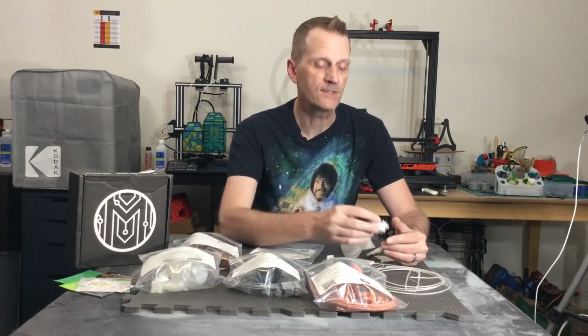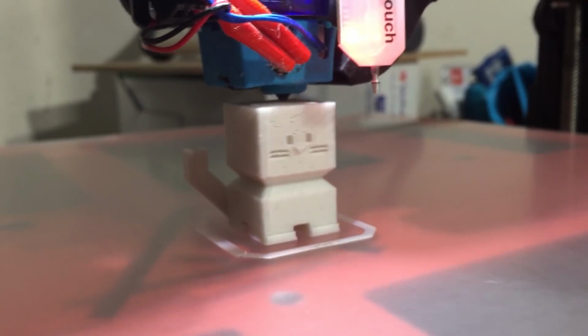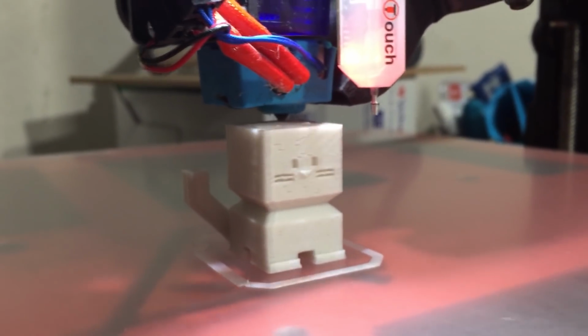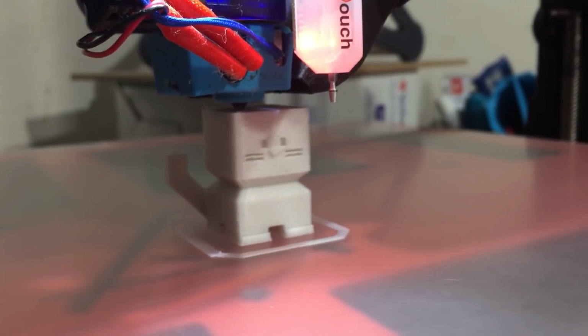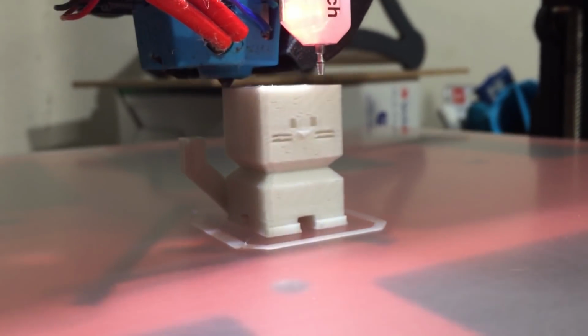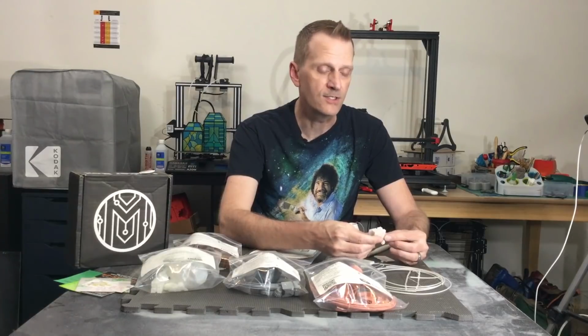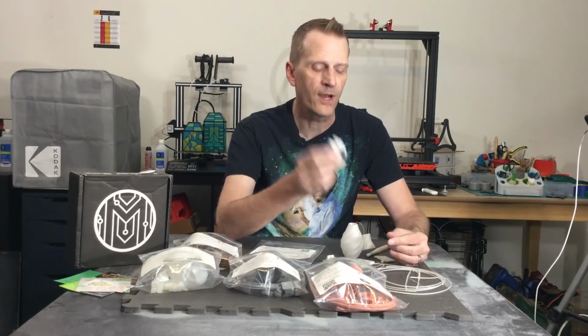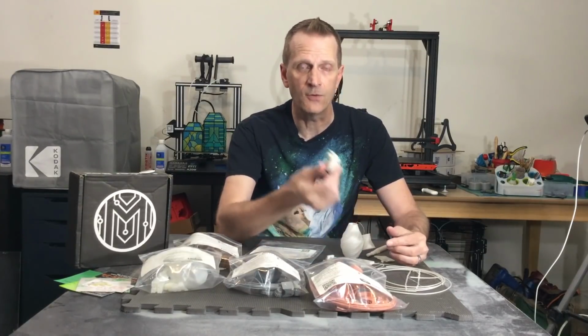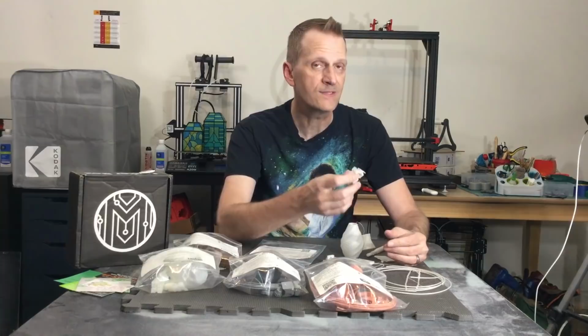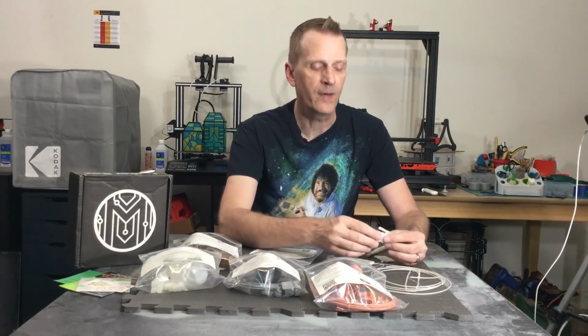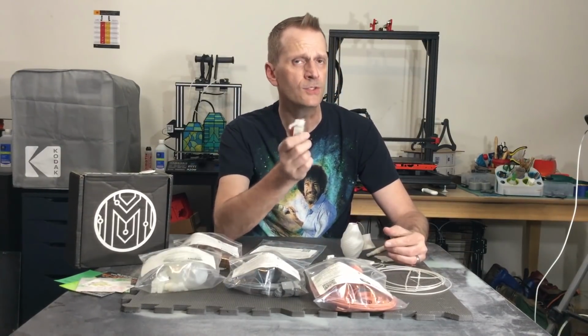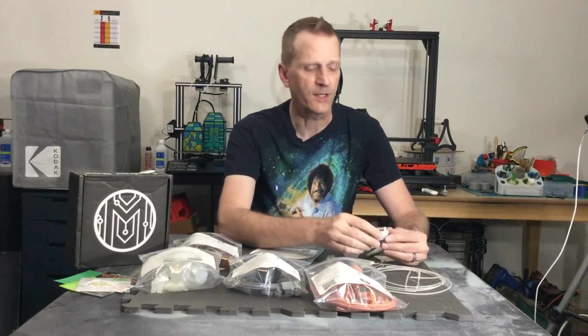But for this, we printed this with 3 perimeters, 3 top layers, 3 bottom layers, and 20% infill at 40 millimeters per second at 235 degrees on the hot end on the cold acrylic bed, and it stuck to the bed too well. Now, it did break at the layers and not at the bottom where I normally suspect it would break. So I thought for sure that it would be a layer adhesion problem, but it's not at that temperature on a cold bed. But it was sticking too well, and I didn't want to ruin my sanded acrylic bed.